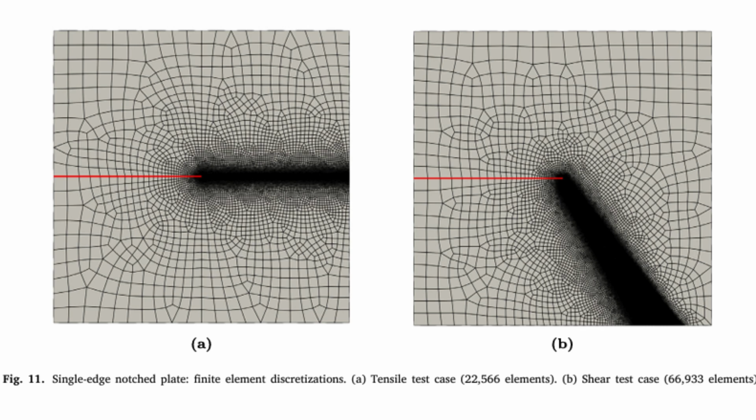That's significant. Any particular standouts? Yeah, a couple are quite memorable. For instance, in the shear test, the SENPS problem, using the CZM model, L-BFGS wasn't just 5 times faster. It was approximately 10 times faster than AM. Wow, 10 times. That takes a simulation from, say, 10 hours down to 1 hour. Huge difference. It really is. And another interesting case was the bending test, S3PBT, with the AT2 model.